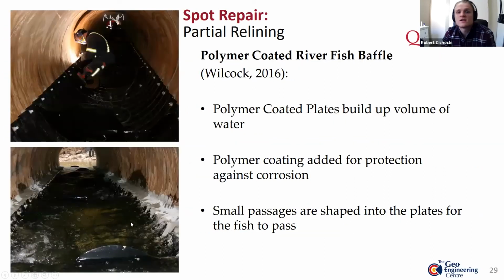When passage for aquatic species also becomes a critical concern, polymer-coated river fish baffle may also be applied to reline the invert of the structure. The polymer coating is laminated to the plate, which adds protection against corrosion. So these plates are installed transverse along the length of the pipe. This is so that we can build up the volume of water between the two plates. And they also have these cuts installed in them, which allow for water to flow through as well as fish to pass.